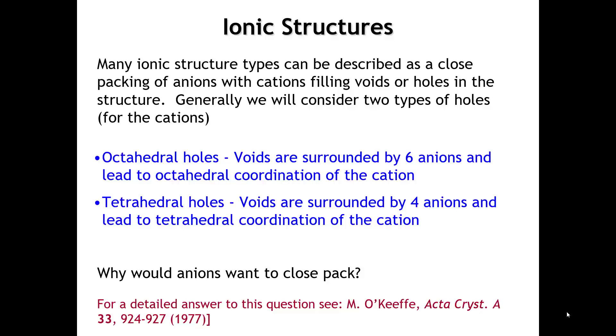One way of describing the structure of an ionic solid is to treat the anions as adopting a close-packed arrangement—either cubic close-packed or hexagonal close-packed. Within that arrangement, there are some voids; about 26% of the space in a close-packed arrangement is voids. We're going to describe ionic solid structures by putting the cations into those voids.